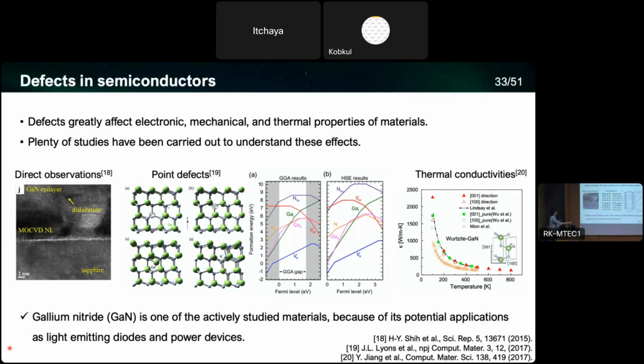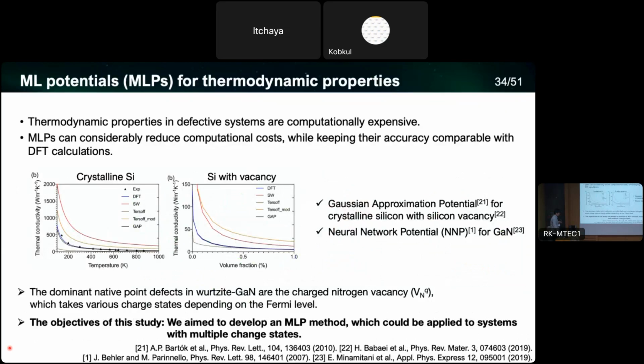And nowadays, the number of studies is increasing focusing on thermal conductivities, which is basically quite heavy calculations using just density functional theory. So machine learning potential may be effective for these calculations. There are already some previous studies doing crystalline silicon or silicon with vacancy, also gallium nitride calculations. But the point here is that, as I showed in the previous slide, specifically in the gallium nitride case, the stable point defect